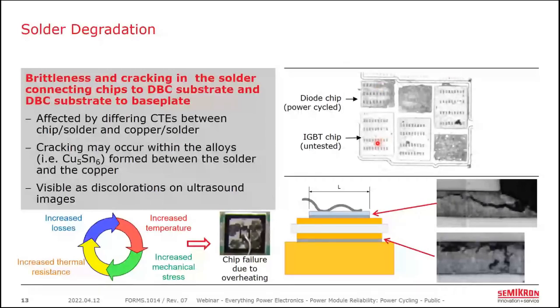And this behavior is sometimes referred to as delamination when it begins at the outer edge of a chip and moves its way in. But on chips with larger areas, it's actually possible for that degradation to occur right in the middle of the chip, as that's where the temperature differential may be the highest.